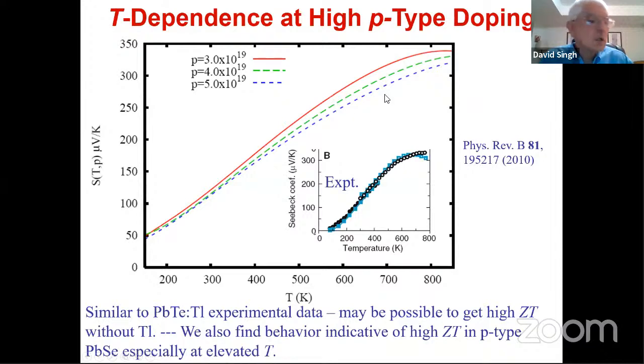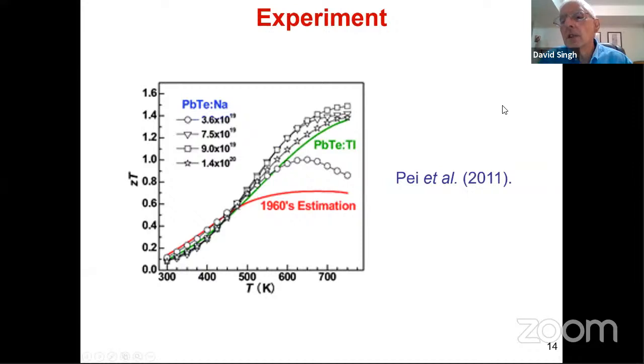This calculation was for lead telluride with no thallium, only with just sodium or some other inert dopant that doesn't change the band structure. And so it agrees. And what that means is that the thallium didn't change the band structure. And what it really was a manifestation that the band structure of lead telluride is not parabolic and is more complicated than people realized. And so what people thought in the 1960s, when the material was industrialized, is that this